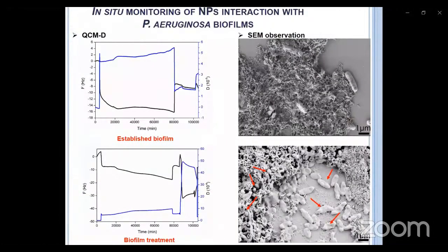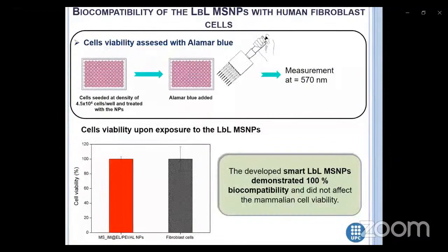So the nanoparticles interaction with drug-resistant biofilm was also in situ studied using quartz crystal microbalance and SEM observation. And as it can be seen, the layer-by-layer mesoporous silica nanoparticles were able to penetrate the biofilm structure, degrade the extracellular polymeric matrix, and kill the bacteria due to the antibiotic release upon the virulent factor production from the pathogen.